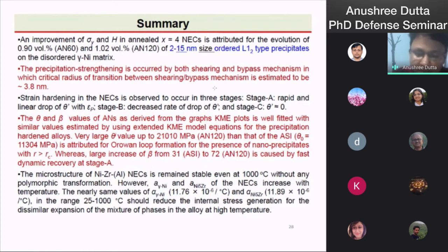The microstructure of the nickel zirconium NEC remains stable even after 1000 degrees centigrade without any polymorphic transformation. However, the lattice parameters of both gamma nickel and Ni5Zr increase with temperature. Nearly the same value of the coefficient of linear thermal expansion for both phases should reduce the internal stress generation from dissimilar expansion of the mixture of phases in the alloy at high temperature.